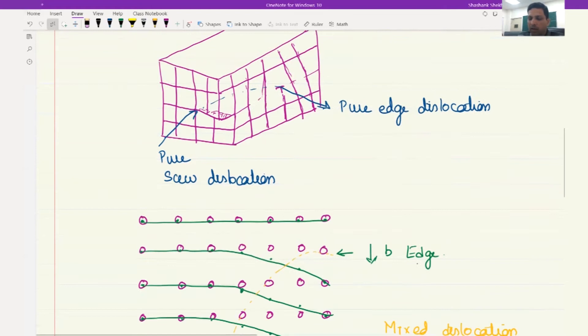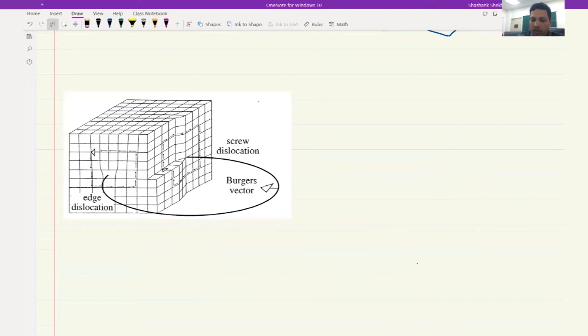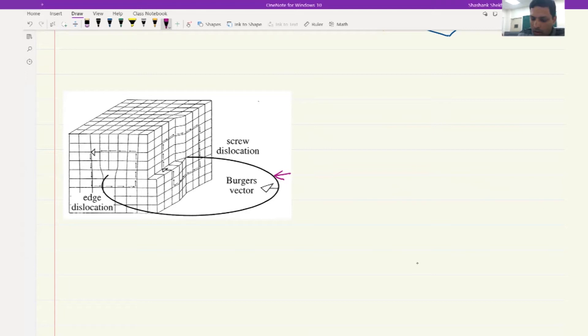It is not very difficult. Using a picture from one of the books, you can see the pure screw dislocation on one side and the pure edge dislocation on the other. If you use the convention we discussed earlier and draw the Burgers circuit, you are able to get a Burgers vector. Using the same convention and the same sense of direction, you also get a consistent Burgers vector for the screw side. The Burgers vector will come out to be consistent — that is the purpose of using the Burgers circuit and convention. So that brings us to a complete understanding of mixed dislocation.